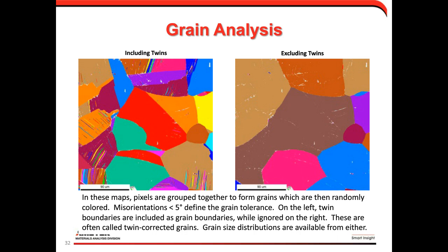And that's just important because for certain material properties, your twins can have a very different effect on properties than, say, a random high-angle boundary. And so being able to calculate grain sizes from one to the other is important.